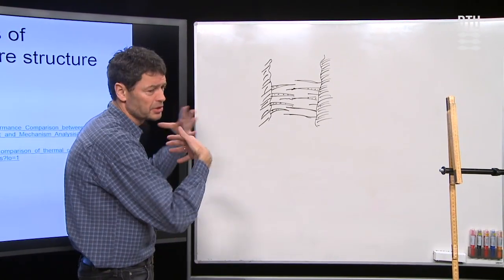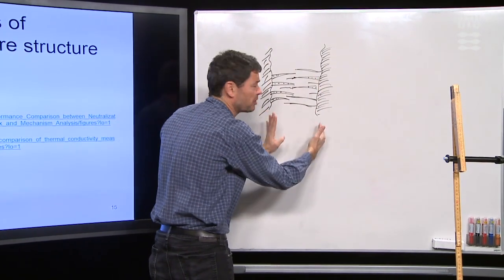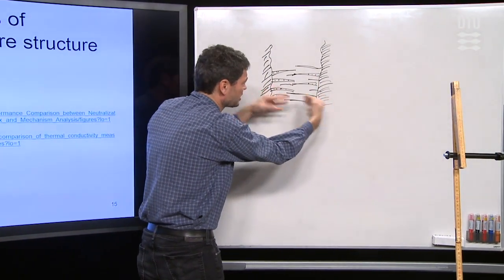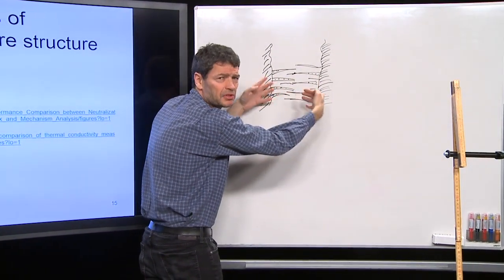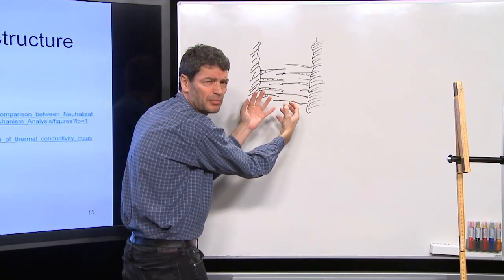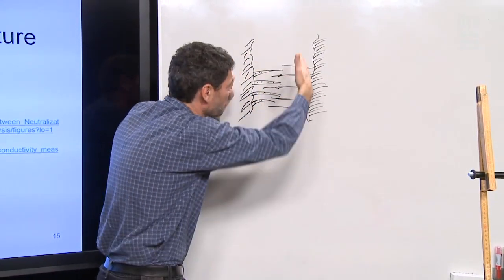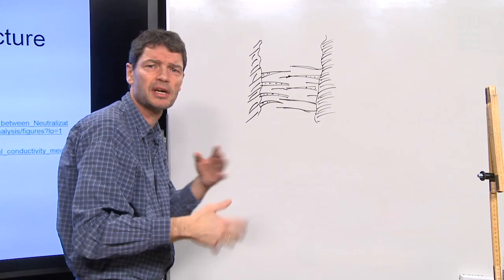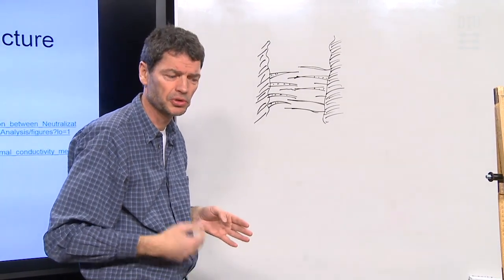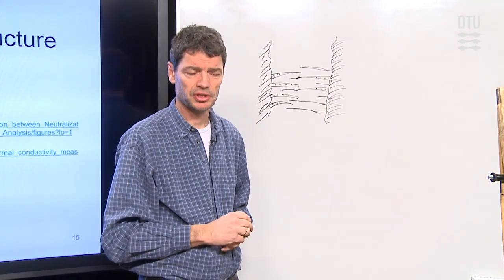expect to see. So on a microscopic scale, the calcium silicate has some large pores, they're rather wide, and inside of those pores are some filaments of small material that function like fine pores, so they can absorb the moisture very strongly, and also the wide part of the pore functions as this motorway, highway for liquid moisture transport. So that makes it very active for capillary moisture uptake.